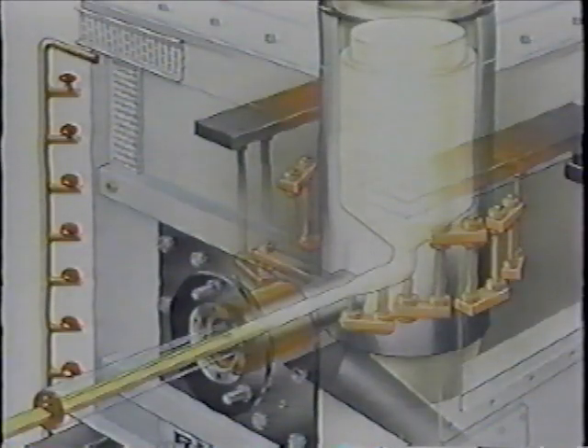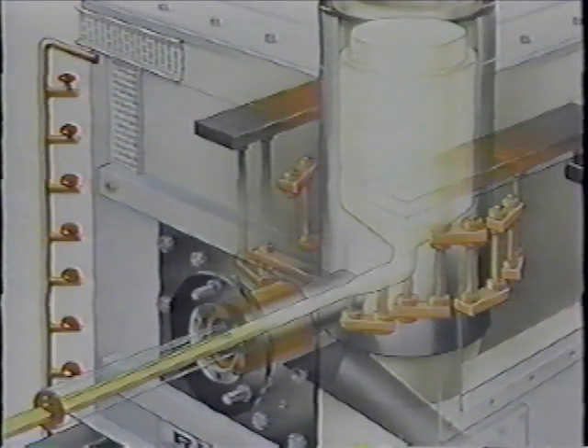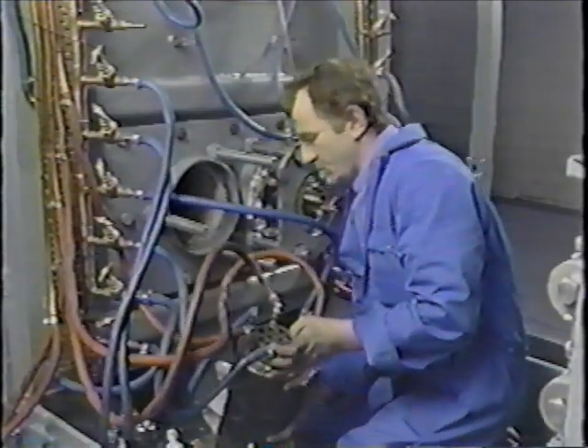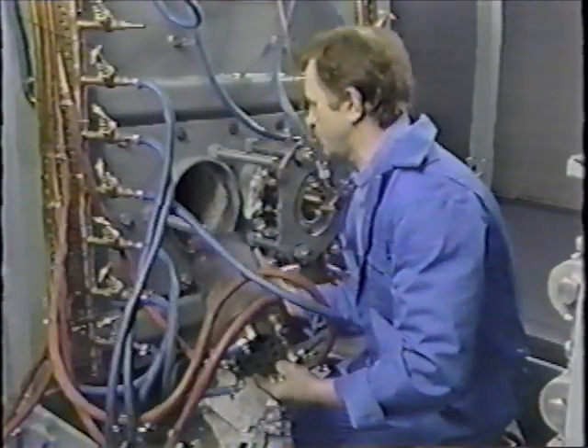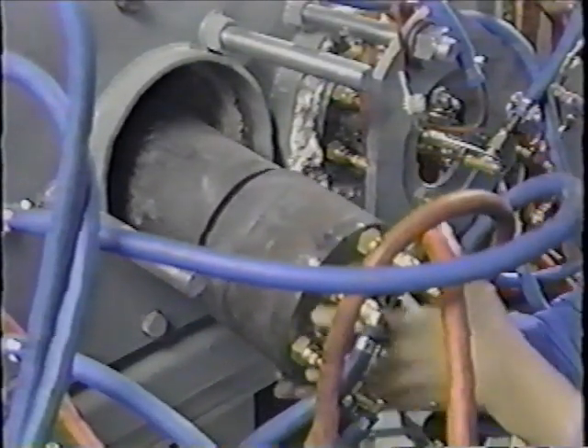Graphite crucibles are self-draining and are expected to have a working life of 1 to 2 years. Where graphite would be attacked by aggressive elements, it is also possible to provide crucible linings or crucibles in other materials, including silicon carbide and clay graphite. The casting dies are supplied as two-part assemblies comprising water jacket or probe cooler systems and graphite casting die.